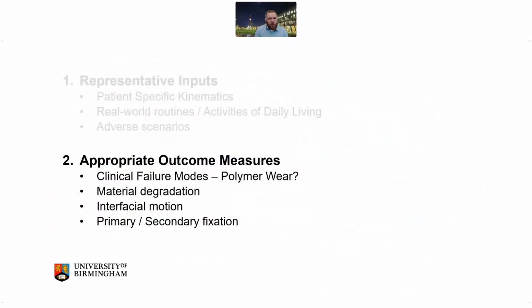So the second stream of what we've done is basically to try to get more appropriate outcome measures than just polymer wear from these simulators. So trying to simulate appropriate or observed clinical failure modes beyond polymer wear. We've looked at retrievals, an extended number of implant retrievals where the devices have been removed for wear, but actually the bearing surface doesn't look that damaged. Or we've had devices where the reason for revision was not wear, but when you actually look at the component, there is a significant amount of damage there. So there's a tenuous link between the clinically reported outcomes and what the device actually looks like.